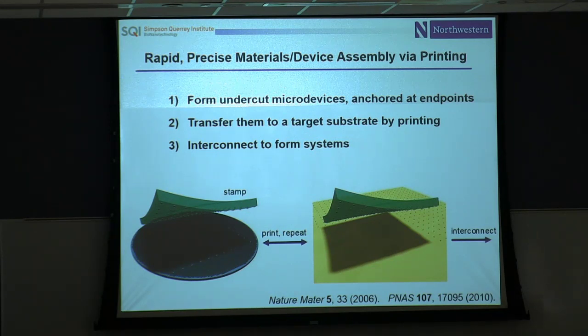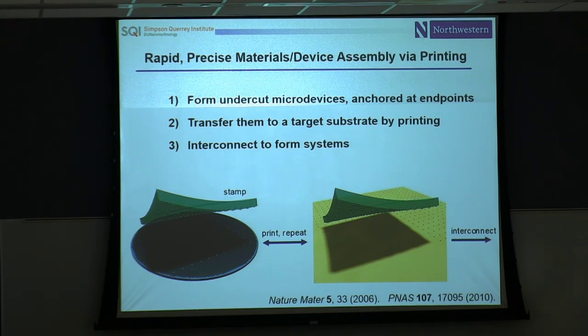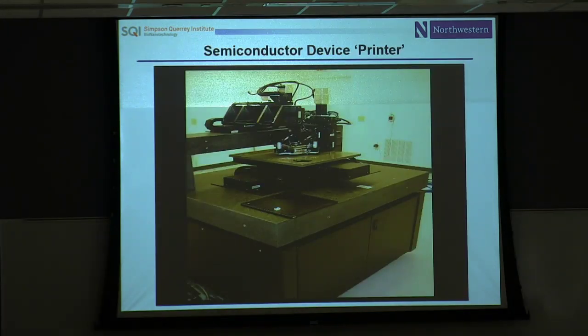The key is controlling the mechanics of soft adhesion. You want a very strong adhesive force to lift elements from the wafer at high yields, but not so strong you can't get them off the stamp surface. There's a set of research concepts we built out over the years that allow you to switch adhesion from strong to weak. These are used in high-volume manufacturing of micro-scale LED displays by X-Celeprint, XDisplay, and others, using an automated system with vision cameras for registration and overlay.